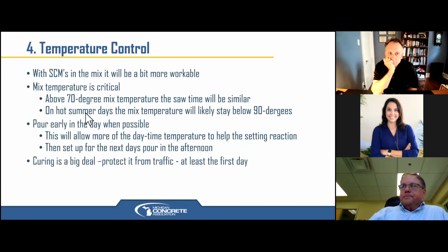Temperature control. With the supplemental cements, maybe not so much as adding the type 1L, but with the supplemental cements, mixed temperature is much more critical. Above 70 degrees, our concrete's going to set up and perform like we normally expect it to. And on hot summer days, we're never going to usually get to 90.